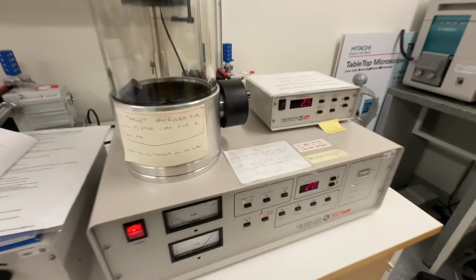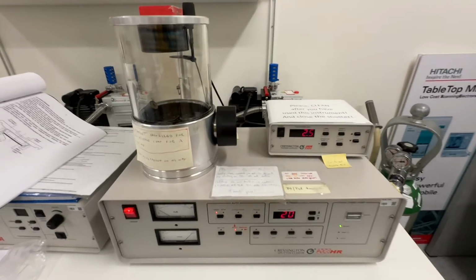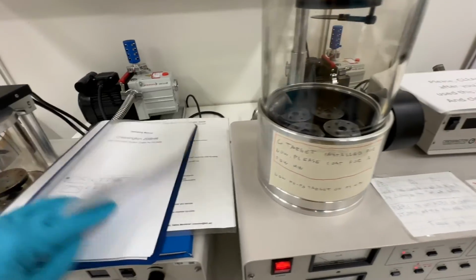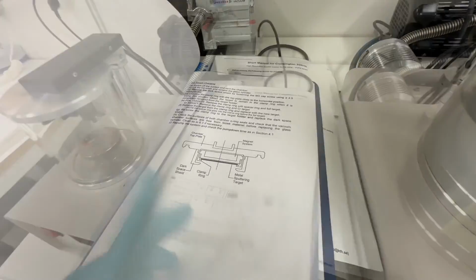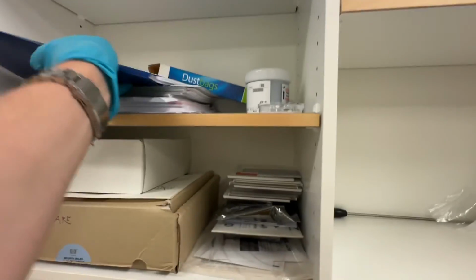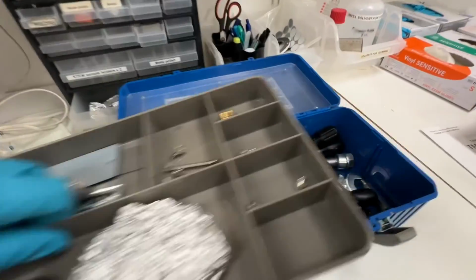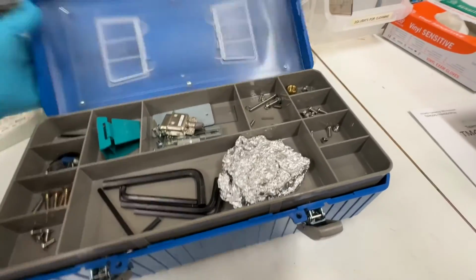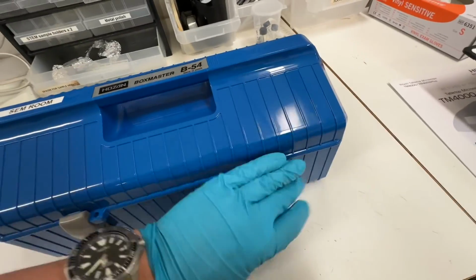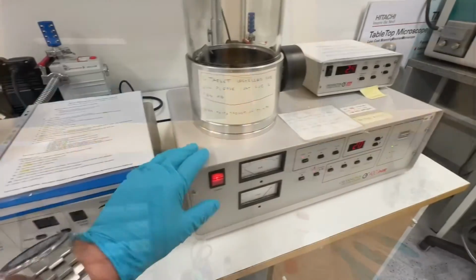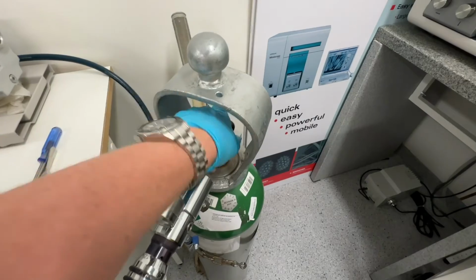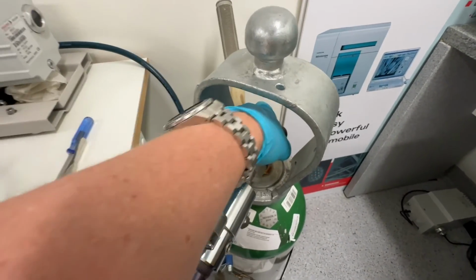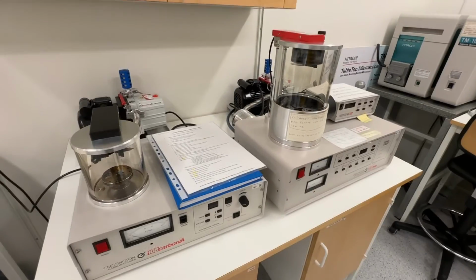That was 20 seconds of sputtering, which should be equivalent to about 3 nanometers of platinum palladium coating on your sample. So we have accomplished the changing of the target, and if you have any questions, there's a very simple manual. Hit it up here in the corner. The tools, Allen key, can be found in here. Shut off the machine and you close the gas. And that's it. Good luck, guys.